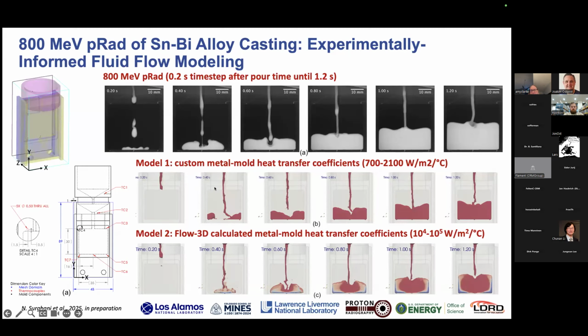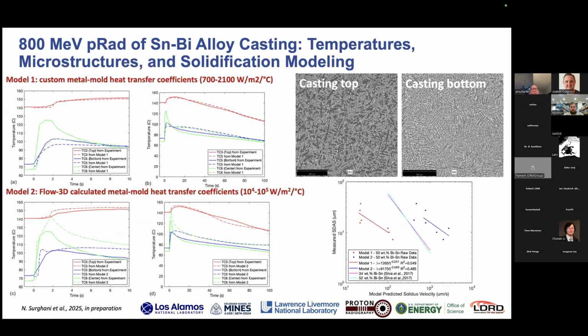And so this is an example of work done by my student Nadira Shragani, where she's taken this PRAD movie and she's done some Flow 3D cast modeling using different assumptions about the metal mold heat transfer coefficients to match with the experiments. And in this case, actually, Model 2 ended up better matching the fluid flow we see in the experiments. And then, as I mentioned, we load this up with thermocouples.